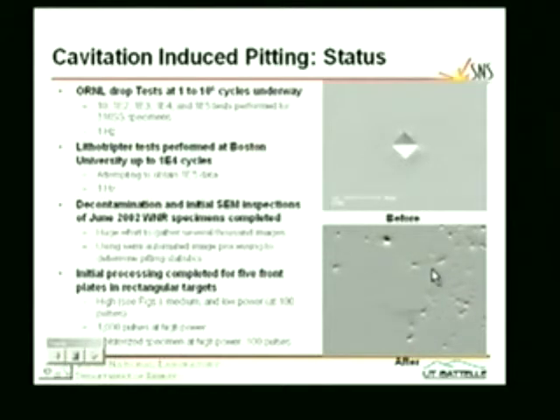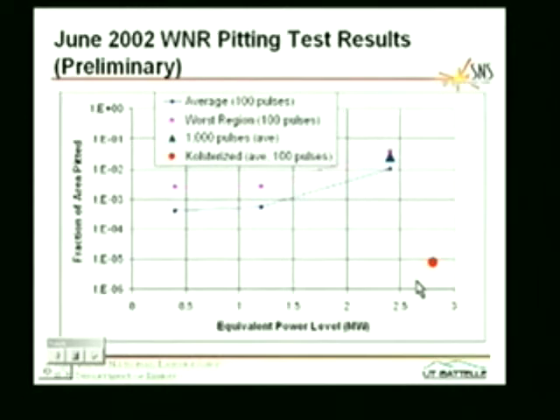These are actually pits that have been excavated by mercury collapsing back into a void that's opened up due to the pressure waves traveling around in the vessel and the stainless steel. And so the issue has been, does this happen often enough and severely enough that it erodes the vessel? So we've had an extensive program looking at beam tests and also mechanical tests up to high duty factors to understand that. And the results are looking quite promising.